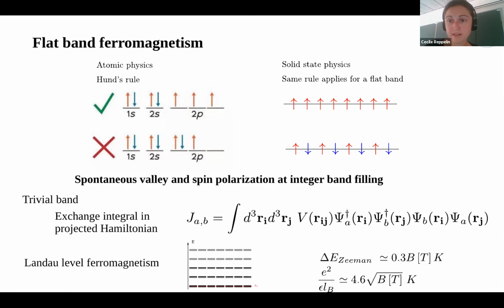But away from that context of the trivial band, you can also think of the case of Landau level ferromagnetism. So this is what I was mentioning in the very beginning of the lecture. When you have Landau levels, you have a spin degree of freedom. And if you consider the case with filling fraction 1, you completely fill the lowest Landau level, but just corresponding to just one spin. Since you have a Zeeman effect, you could naively think that the fact that you have an insulator in this case, the gap comes from this Zeeman effect, but it's really not the case because the Zeeman effect is very small in energy.